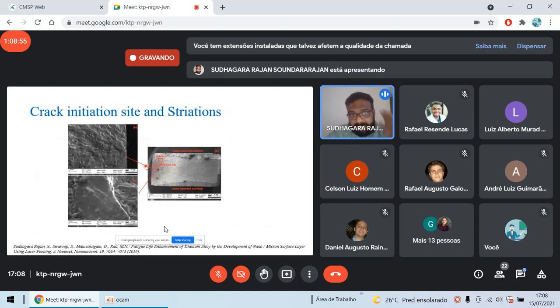And this is another image from research I did. This is a fractography analysis of a fatigue failed specimen. It is a tensile fatigue test, and two sides are laser peened. Laser peening is the process of imparting compressive residual stress in the near surface region. So in this region the crack doesn't initiate, but on the side where the compressive residual stress is not there, the crack initiates. You can see that. From there the crack propagates, and these are all the final fracture area.